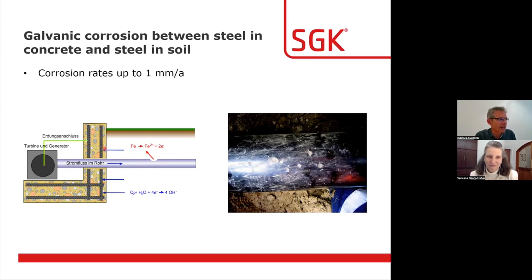And you have it in the same electrolyte, being the soil, and you have the flashlight being switched on through the equipotential bonding. And that gives you what you see here, holes with a depth of about 6 millimeters within 6 years of operation, because the current flows from the pipeline into soil to the cathode over the earth equipotential bonding and drives the corrosion process. So that's one type of damage we're looking at due to the connection of steel in soil with steel in concrete. So you learn immediately galvanic corrosion is not limited to issues between copper and zinc. You can happily build galvanic corrosion between the same type of metal, provided it has a difference in potential.